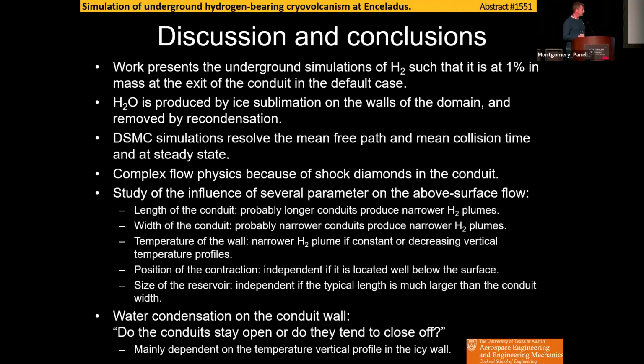I have to say this is a work in progress, from which we saw that the width of the conduit and the temperature of the wall are probably the most important parameters. A narrower conduit will lead to a narrower plume at the surface, same for the length of the conduit, and for the temperature of the wall. It's narrower if the temperature is either constant or decreasing while going up. Position of the contraction inside the reservoir are less important parameters.